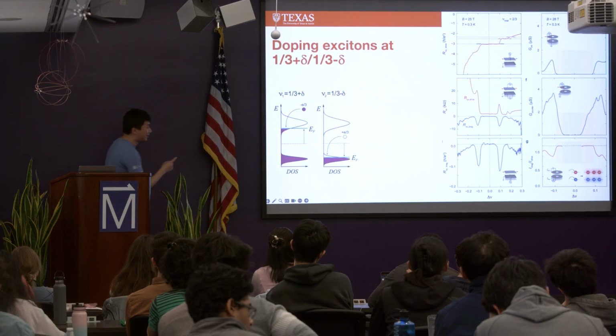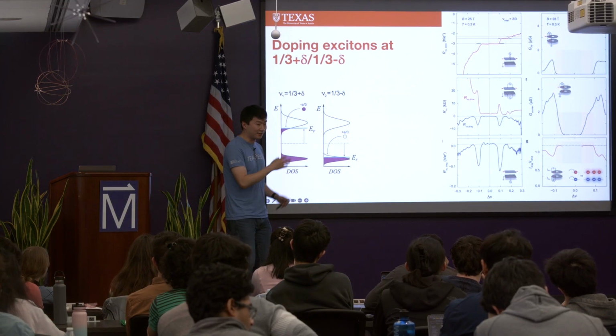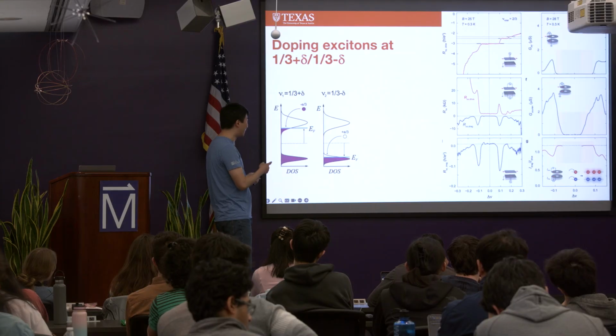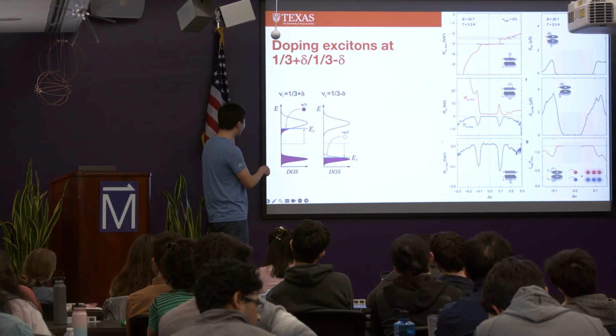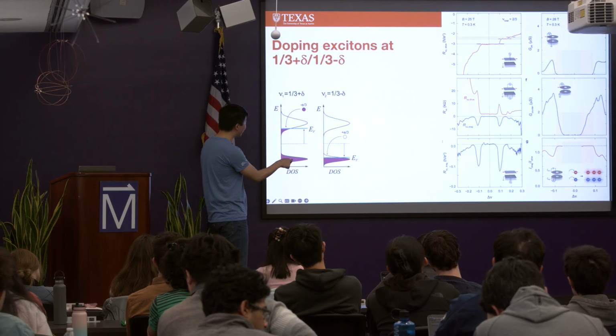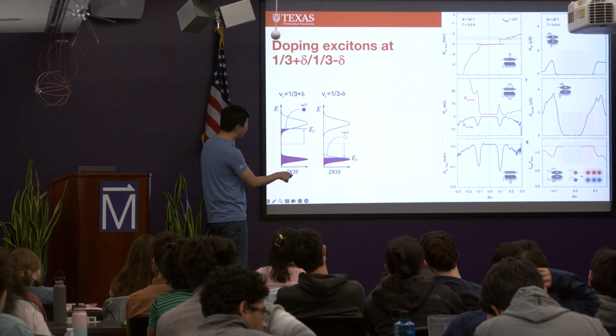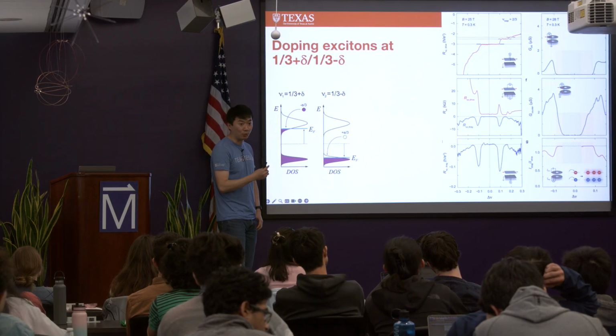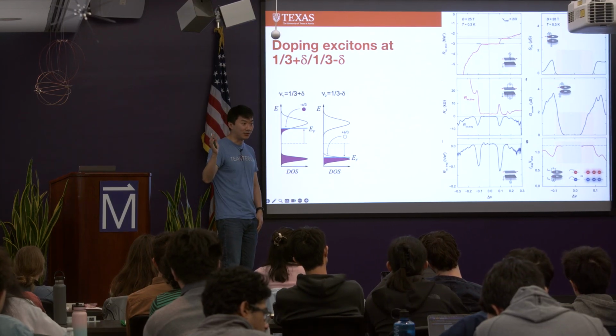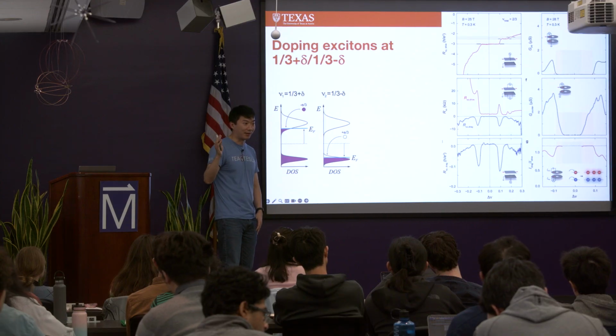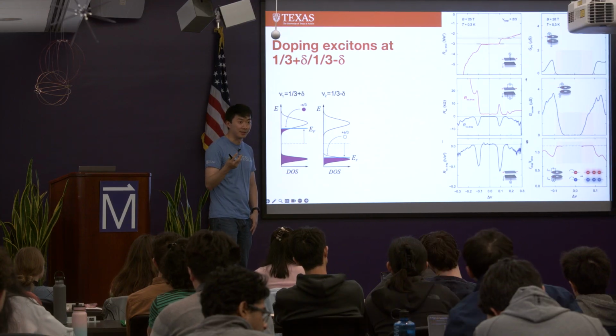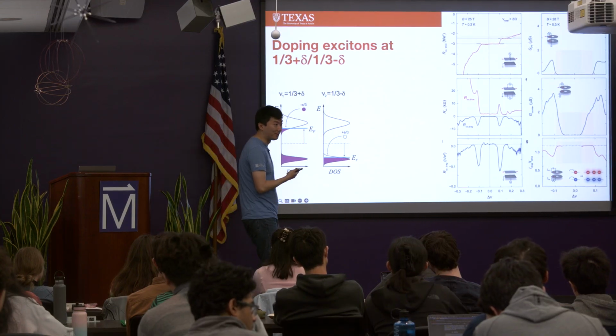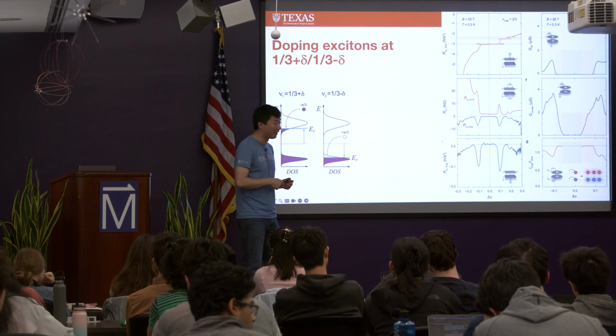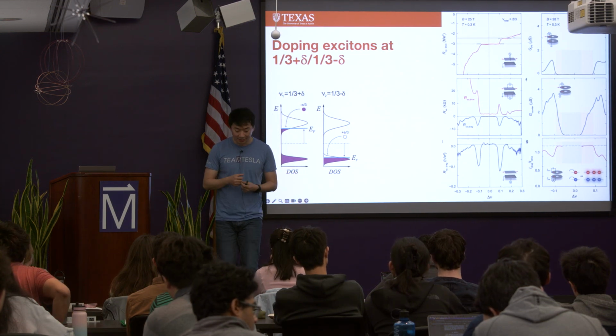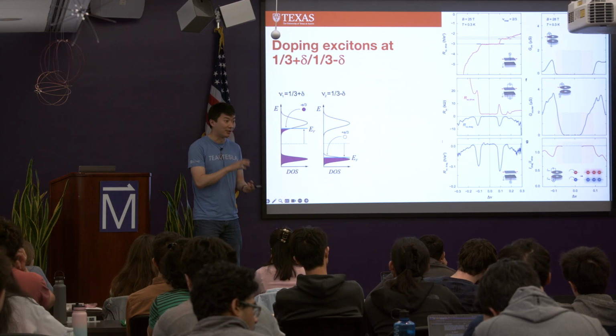Right. You can actually test this in a number of different ways. I didn't put the data in here. For example, you can start from this point where there's a very robust charge gap and just warm up in temperature. And right around the time the charge gap closes, you also recover this perfect drag response, which means that, right, you can create quasi-particle, quasi-holes either by doping or by thermal activation.